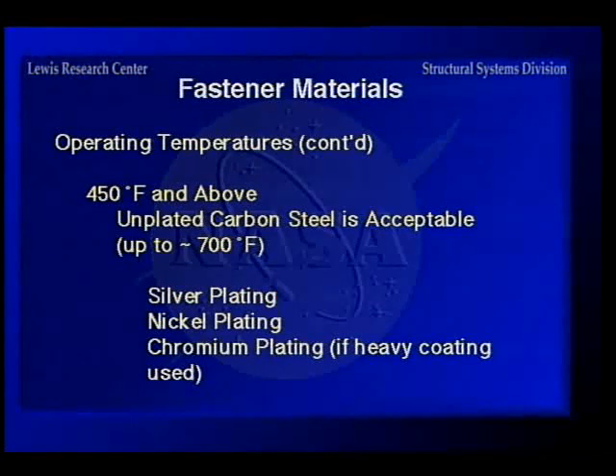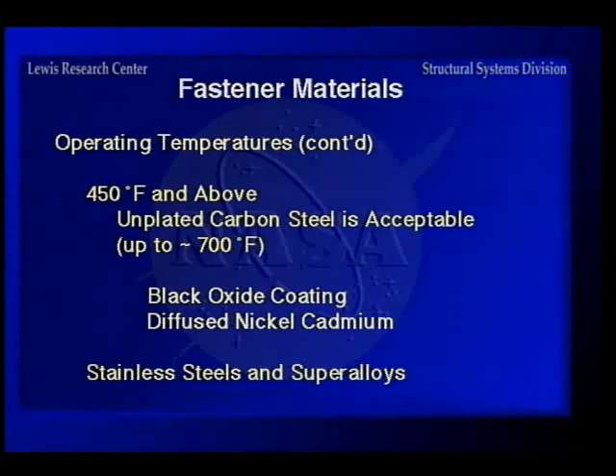Now, I'm just giving these because of their temperature range, rather than the fact that you normally wouldn't silver plate a carbon steel, but you do silver plate stainless steel. But silver, nickel, chromium plating, and chromium plating is used on some high-strength fasteners for aircraft landing gear, that type of thing. The black oxide coating that you're all familiar with from your hardware store bolts looks good and all that, but it burns off. Then you have diffused nickel cadmium, which is a special one that will be covered later. And then, of course, you can use the stainless steels and super alloys without anything.